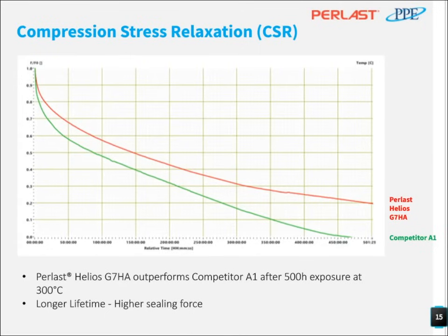Okay, as I explained in the last slide, the initial force drops by the time at 300 degrees Celsius in this case. As you can see, Perlast Helios material performs significantly better than the competitive material. This Helios material retains a lot higher force than the competitive material for longer period of time.